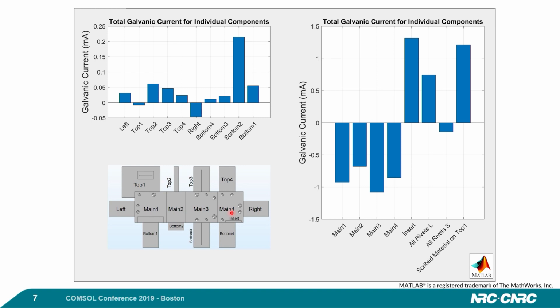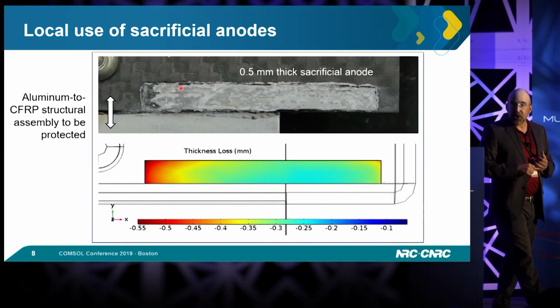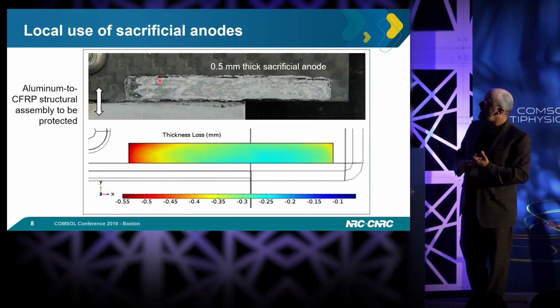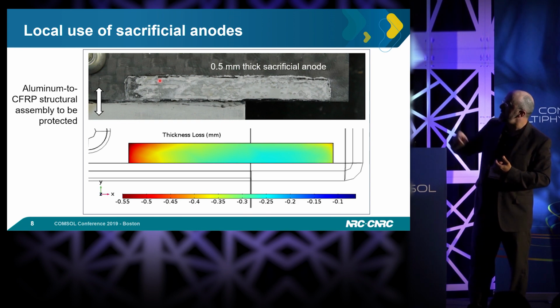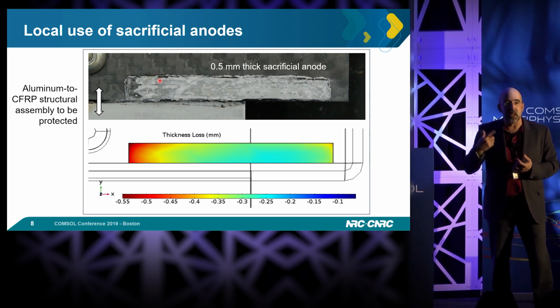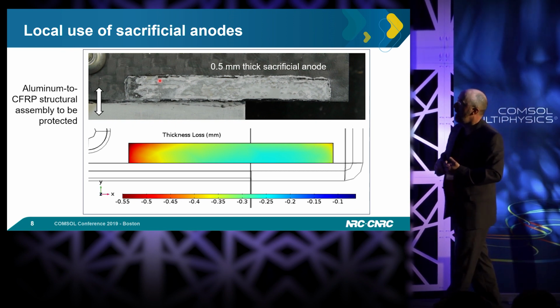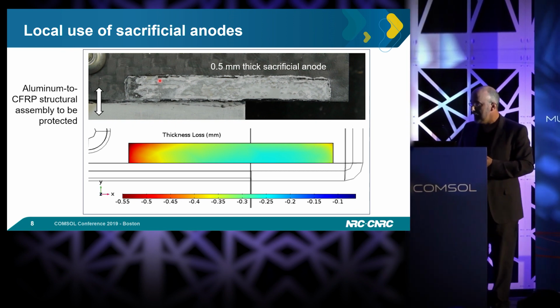So what we would like to have is a very low anodic current on bottom four and a very high anodic current on the insert. And this is what we do have here. If you look at the insert, the total current that flows is roughly 1.25 milliamps. And bottom four, it is pretty low, a few microamps. So it does its job by protecting the substrate it has to protect. Now, does it work? Initially, this sacrificial material was 0.5 millimeter in thickness. You see down here the thickness loss as a function of time during the lab exposure. So we have a good agreement between the model and the lab tests.